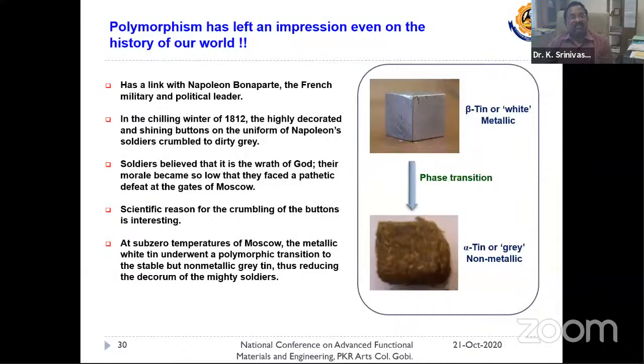After a period, because the temperature at Moscow was sub-zero, just because of the very cold environment, this white metallic tin was transformed into the other form, alpha tin. It becomes gray in color. The soldiers believed that it was the wrath of God. So their morale became so low that they faced a pathetic defeat at the gates of Moscow just because of this polymorphism.